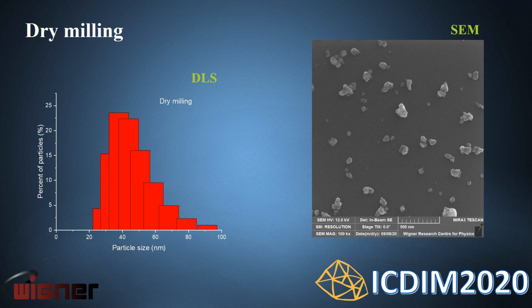The size of the dry milled sample was mainly 30-40 nanometers, in the range of 20 to 80 nanometers. This SEM picture shows the crystallographic morphology, in this case too. This sample was diluted to an appropriate extent, so the particles didn't stick together.